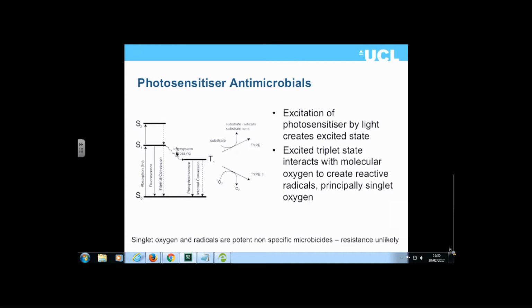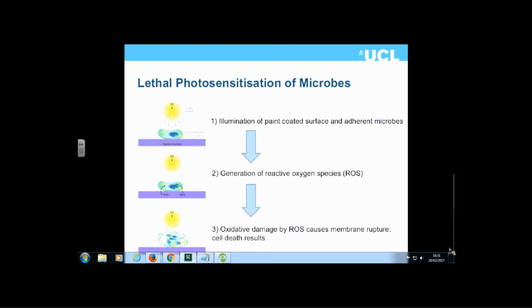Type 1 mechanism is where incoming light takes the dye material to its excited state, and through intersystem crossing and then either phosphorescence or internal conversion, it can lose its energy. This excited state will react with substrates in the environment, such as water, to create hydroxyl radicals, or it can convert triplet oxygen to singlet oxygen. Singlet oxygen is very, very reactive and is able to destroy bacteria.